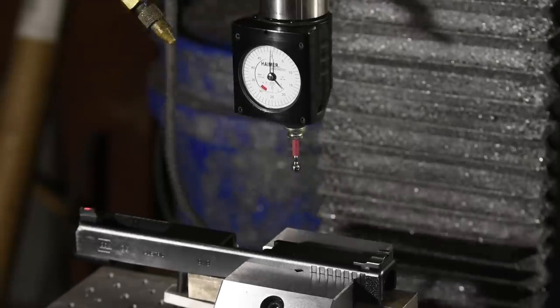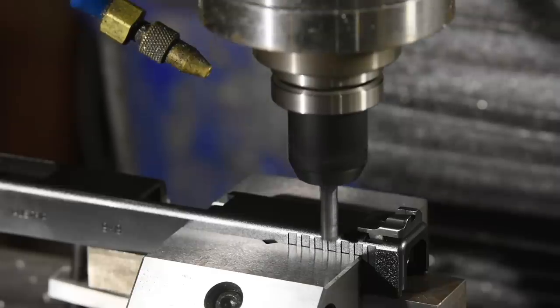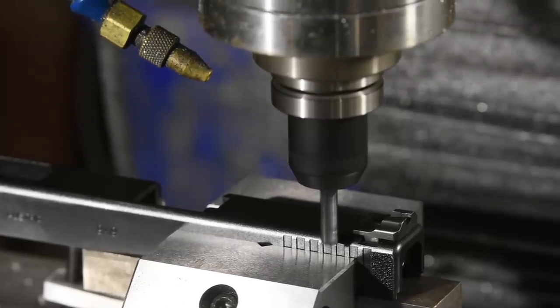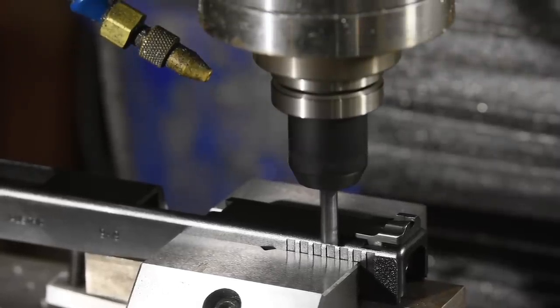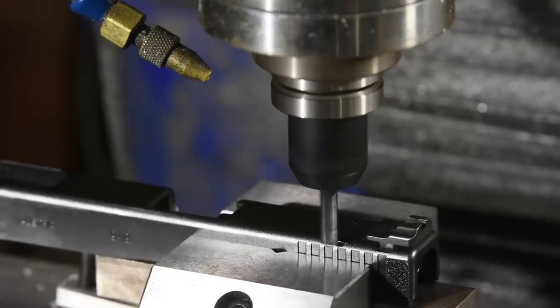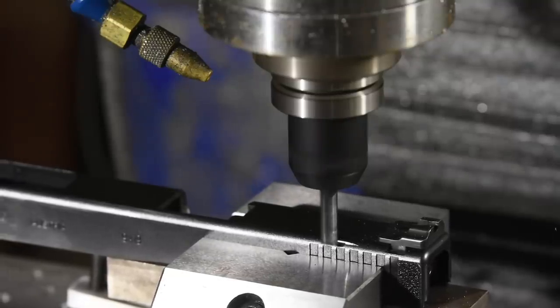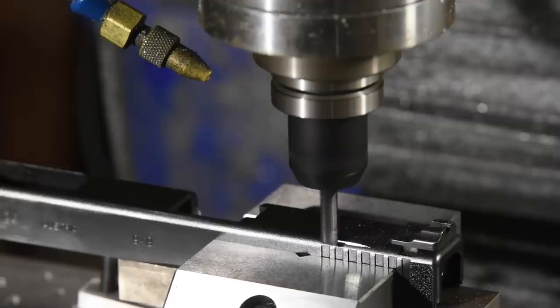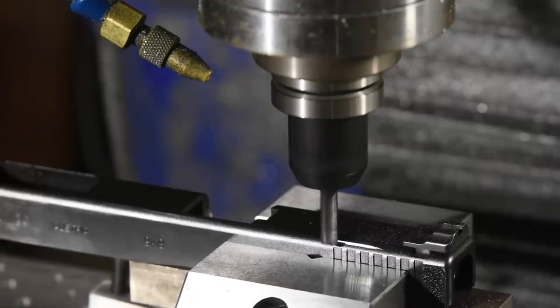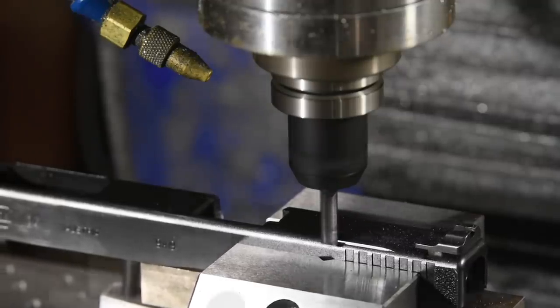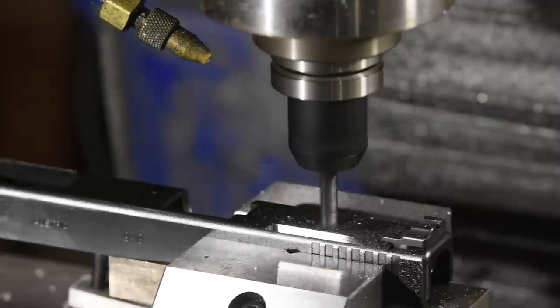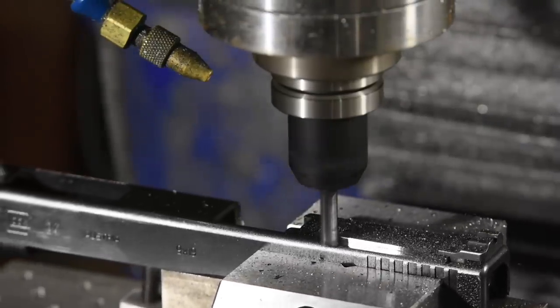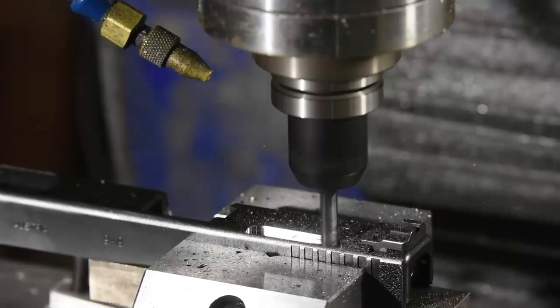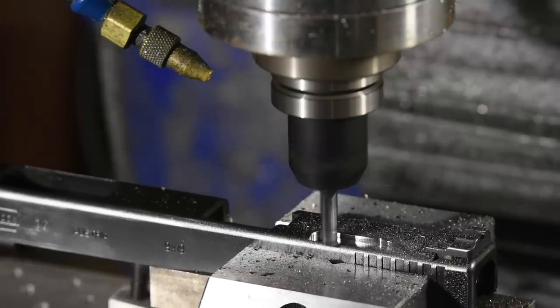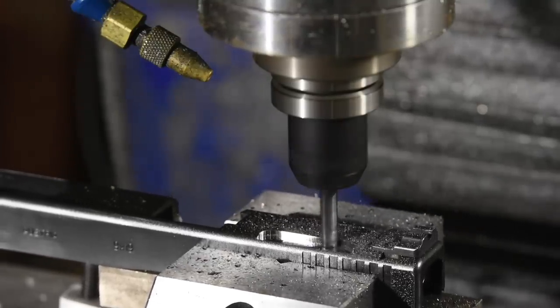I'll rough out most of the slide dry on my Tormach 770 using an adaptive clearing path with a 4-flute, 1/4-inch titanium aluminum nitride coated carbide end mill. I've always heard that Glock puts some kind of really hard finish on their slides, so I Rockwell tested it. If the finish is really hard, it turns out it's not deep at all. So the slide came in at about 35 on the Rockwell C scale. So compared to what I'm used to machining, this is pretty much like butter.